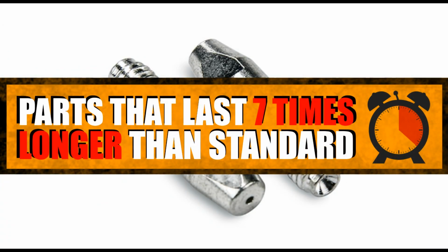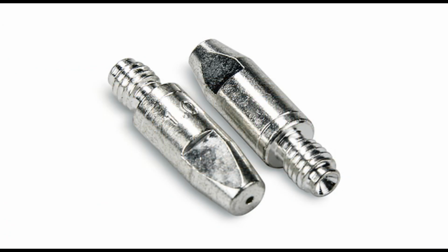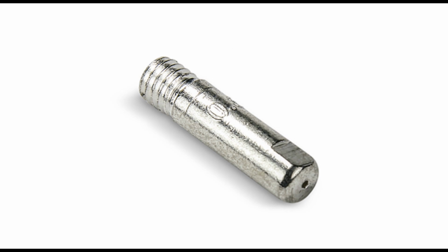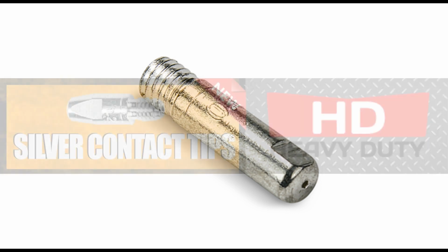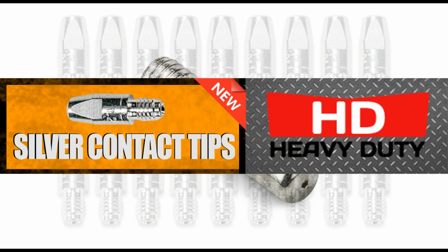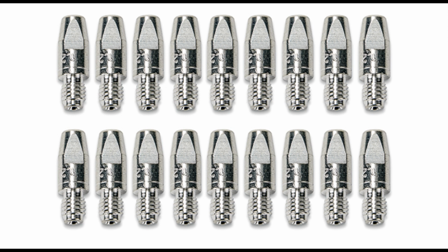Silver is approximately 17% denser than copper. It has a higher melting point. Silver's shiny surface helps to reflect heat. As a result, spatter doesn't adhere to the tip as easily and it doesn't wear down quite as quickly. In fact, the lifespan of a silver-plated copper contact tip can be 7 times longer than the standard copper contact tip.